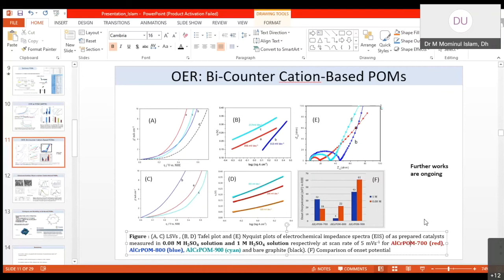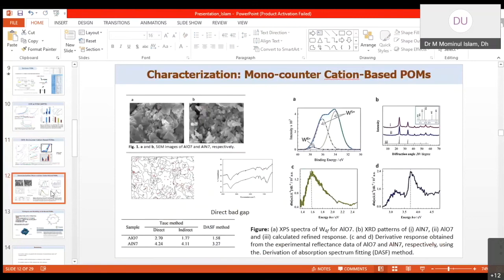So to understand the mechanism, we did further characterization, for example SEM, XPS, XRD, and also some reflectance analysis. We found that this gives a direct-indirect band with low band gap energy, and that this catalyst contains a high percent of tungsten 5 state. It has been known that this is very important, and it is in fact unstable, because tungsten 6 is more stable than tungsten 5.